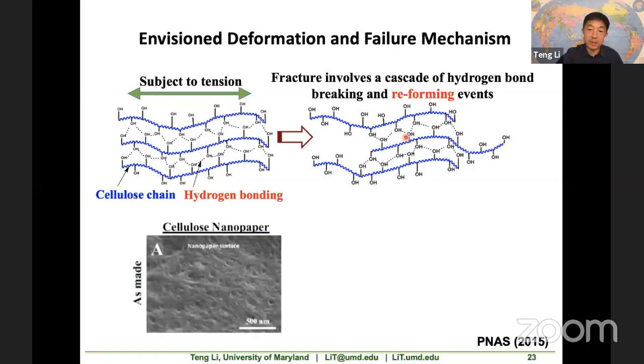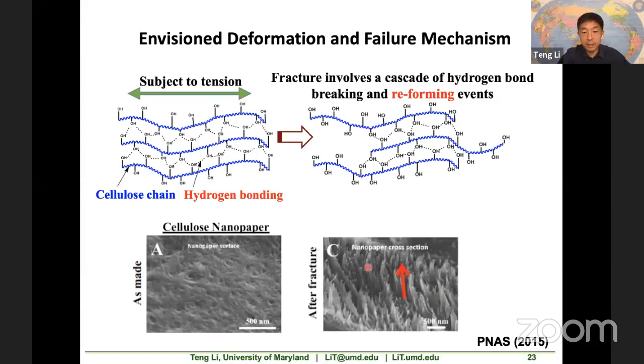And of course, this atomistic scale failure mechanism and deformation mechanism is hard to observe and verify in the experiment, but we can get some indirect evidence from the nanoscale. So this is an SEM image of the cellulose nanopaper as made. As you can see, the cellulose nanofibers are really randomly distributed in the plane. However, when you fracture this piece of nanopaper and look at the fracture surface, you see these very well aligned cellulose nanofibers, which is basically you start with a random distribution of the network of cellulose fibers. When you start to slide and then fracture, they naturally form this aligned profile.